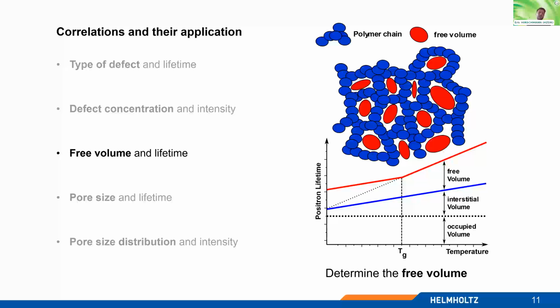What else? Switching the material a little bit, coming from metals and semiconductors, now switching to polymers, or soft matter. And as you can see here, positrons can also help to investigate the interstitial volume as well as the free volume here in blue and red. And for example, if you vary the temperature for these materials, then you can also see that there is a trend, and you can also see if this trend varies. You can define the glass transition temperature, for example.